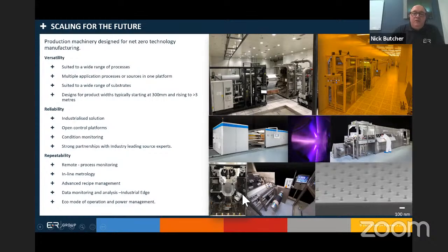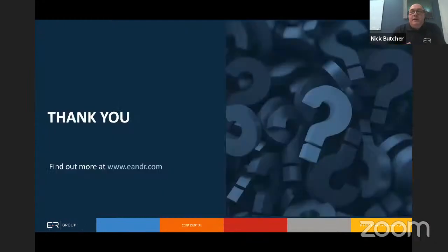We've been developing solid state vacuum coaters with combinations of electron beam and sputtering. And in the far instance here, you can see the scale that we're actually nano manufacturing silicon pillars for graphite replacement layers in silicon anodes, where you can see the scale where we've successfully printed in roll-to-roll down to the 50 nanometer scale. So on that note, I'd like to thank the DSM for inviting me to speak today.